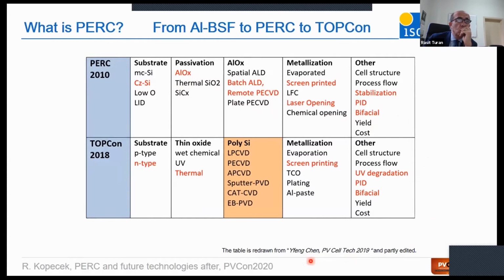And we are facing the same challenges with TOPCon, but still TOPCon is an upgrade of the PERC technology, using N-type substrates, of course, which works better. And then the major question here is what kind of polysilicon to use. LPCVD works, but it's better to have a one-sided deposition and in situ doping, and also a very fast deposition without breaking the quartz tube. So there are some alternatives, PECVD, APCVD, sputtering, and so on.